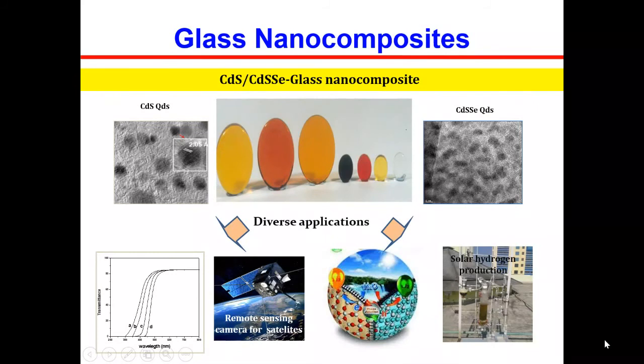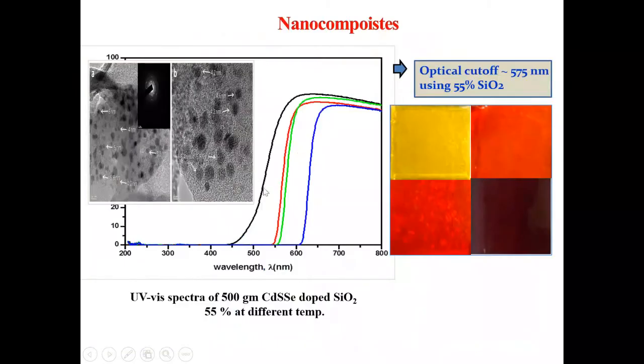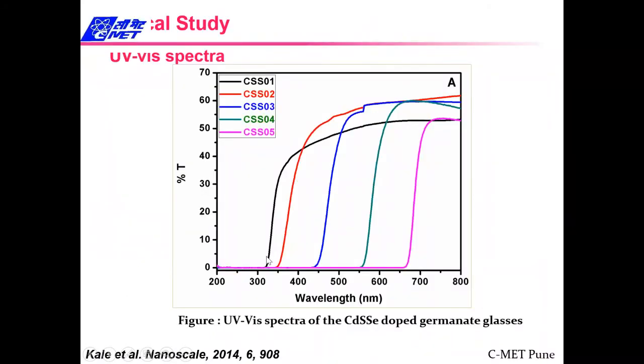Here you can see absorption. You can see the UV region. Initially it is at 300 nanometer. When you have growth of these particles, then we can see there is absorption in the visible region. These are the nanocomposites. See, with color you can see there is a change in color with the size of the cadmium sulfide in the glasses. Here, initially it is a very low concentration and low size.